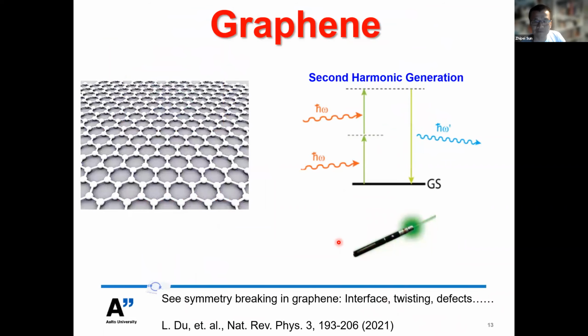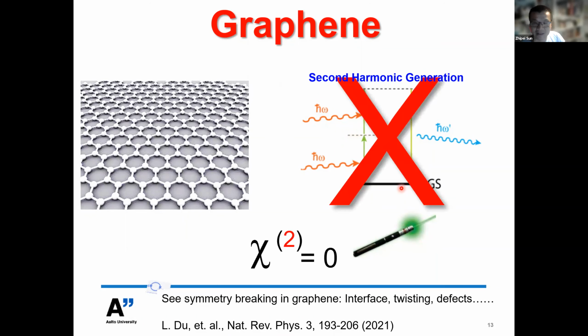But if you want to use graphene for a second order nonlinear process, for example, to generate a frequency which is 2 times larger than the input frequency, this process is called second harmonic generation, which is the process used for the laser pointer. This process is also the most useful nonlinear process for applications. But if you want to use graphene for this process, you will be really disappointed, because graphene doesn't have a second order nonlinear response, because graphene has a centrosymmetric structure, which doesn't give a second order nonlinear response.